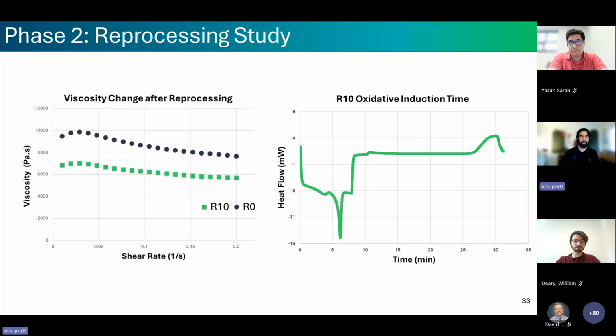To answer this question, we conducted a reprocessing study across 10 cycles, R0 through R10. In this study, we molded tensile specimens, tested them mechanically, rheologically, and thermally, then remilled those samples, molded new samples with that, and then tested again for a total of 10 cycles. We used 2 tests to evaluate the degradation of our material: zero shear viscosity and oxidative induction time. To determine zero shear viscosity, we conducted a frequency sweep on a hybrid rheometer.